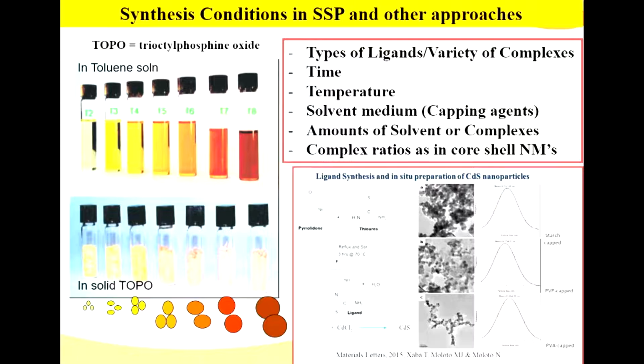And one of the other things that we tried to do with this single source precursor was to ask: what if we can make the ligands in situ? In the process of making the ligand, you don't necessarily have to extract it to see what bonds are forming in it, but just add your salt in situ so that you end up with the same product rather than having a complex forming there. So you just go in the reverse of the single source precursor route, in a way. And you manage to get that and vary it, even the capping molecules that gave rise to it. Although there's some bit of agglomeration, varying the conditions essentially improves those nanoparticles even further.